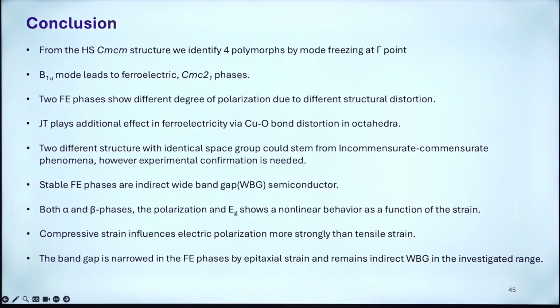These 2 ferroelectric phases show different degrees of polarization due to different structural distortion. Apart from the structural distortion, based on these distances we do see that the Jahn-Teller kind of distortion plays an additional role in enhancing the ferroelectricity, in the copper oxygen bond distortion in the octahedra. These 2 different structures with identical space group could stem from incommensurate to commensurate like phenomena. However, this is only a hand waving argument. I am not trying to confirm it because this needs experimental confirmation.